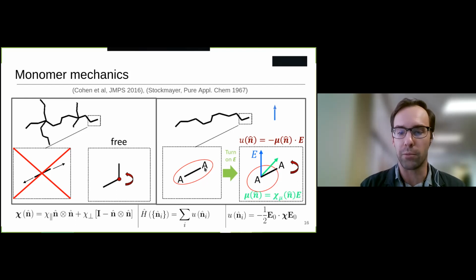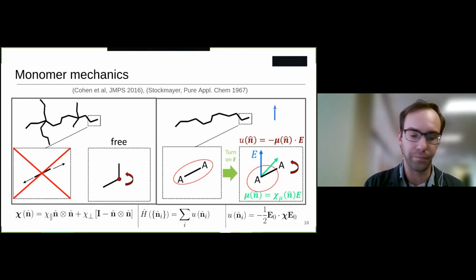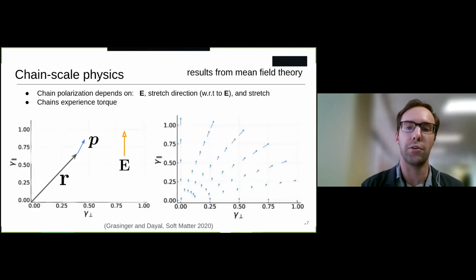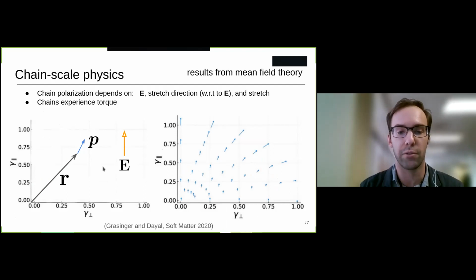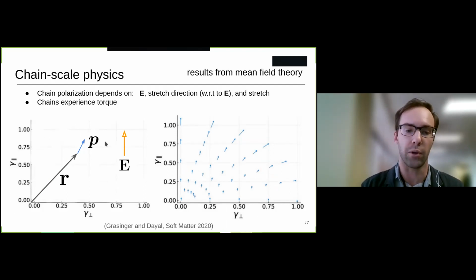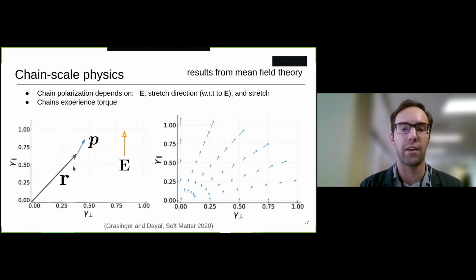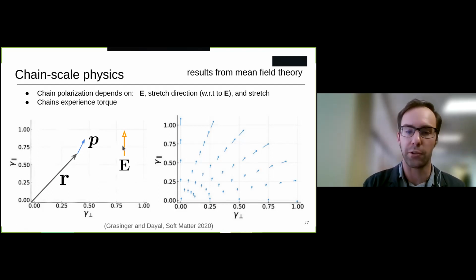You can almost think about these monomers as having some electron cloud, and when you apply an electric field that pushes this electron cloud in a certain direction, we now have a net positive charge on one end of the monomer and a net negative charge on the other end. And so you can see some interesting things when you solve the statistical mechanics problem here. One in particular is that the polarization response of a single chain can often be misaligned with the electric field direction. And that leads to an electrostatic torque because the chain wants its polarization to be aligned with the electric field. And so you actually get some stress and some torque that develops in the chain itself in response to the applied electric field.